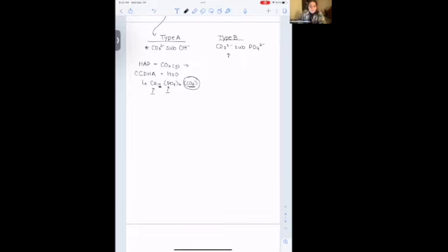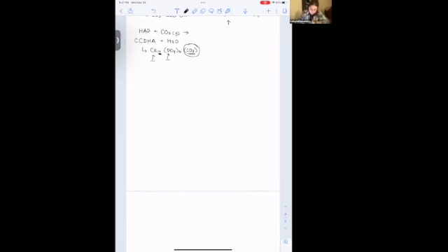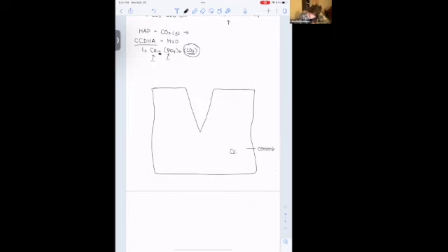And so what the researchers did for their self-healing concrete was they were trying to create these CCDHA and CDHA molecules as their healing paste between the concrete. And so if you imagine a little slab of concrete with a crack in it, right? You have your concrete or cement, which contains calcium carbonate. So there's your source of calcium ions. And they put within that this hydrogel that contained phosphate. So hydrogel with phosphate, HP.